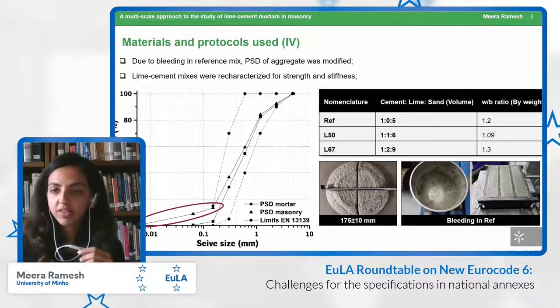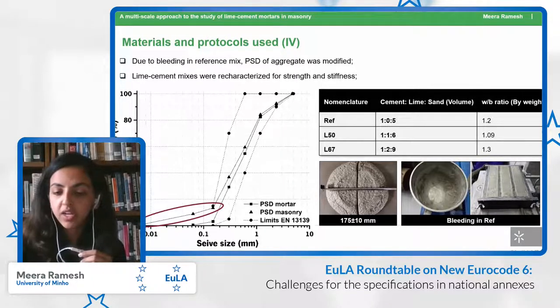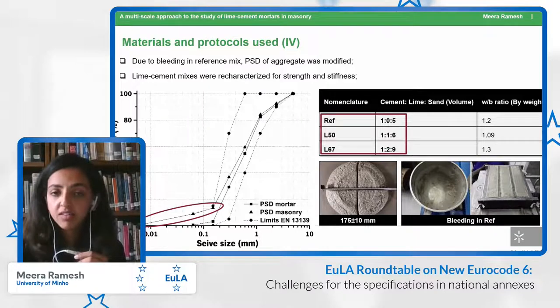So for the masonry level study, we had a reference cement mix and we selected two lime cement mixes, which we had to recharacterize with the new aggregate. So what we studied at the masonry level was a reference mix with composition 1:5 and two lime cement mixes with composition 1:1:6 and 1:2:9.